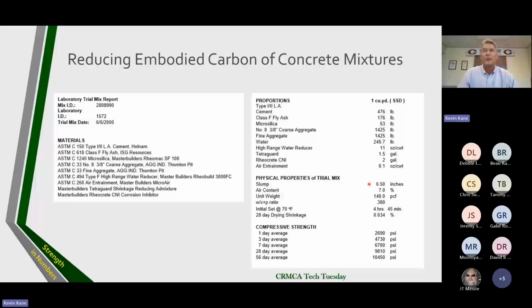6.5-inch slump, 7% air, 140 pounds per cubic foot. And that water cement ratio for this amount of cementitious is not ridiculously low. A 0.38 is not terribly low water cement ratio. I measured my initial set because that's going to mean something to the contractor who may have to build something with this concrete. Pretty normal concrete set time, 4 hours and 45 minutes. Look at the drying shrinkage I got from the 1.5 gallons of Tetraguard. I got a 0.034 drying shrinkage at 28 days.